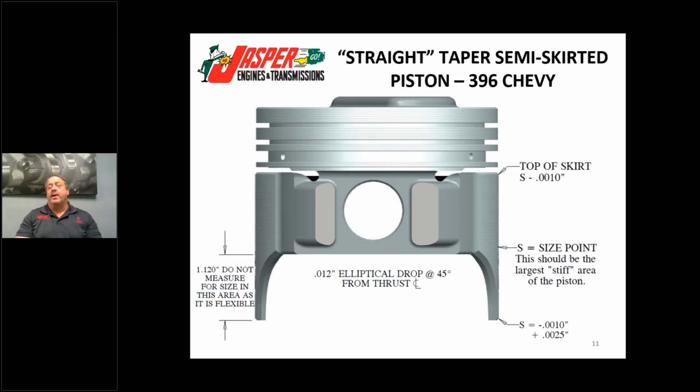If you have the rings where you've got the waviness under control, where you don't have any more than 3/10 waviness in the grooves, and you're running 1 thousandth side clearance, that stabilizes those pistons a lot. And then when you put skirt coating on it, you know, that is my deal.